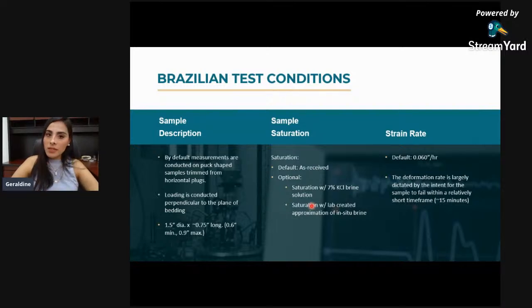The strain rate of this test, the default or standard, is 0.060 inches per hour. How do we determine this? You want your sample to fail in a short time, more or less 15 minutes. So this strain rate was determined with the intent that the samples fail in this time.